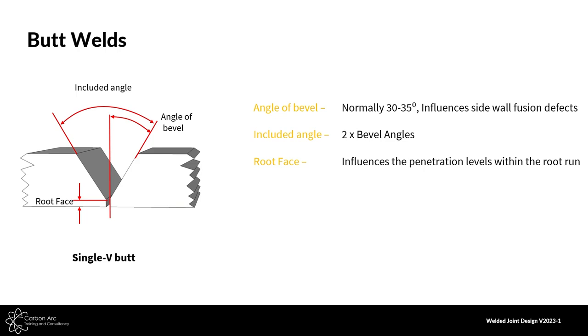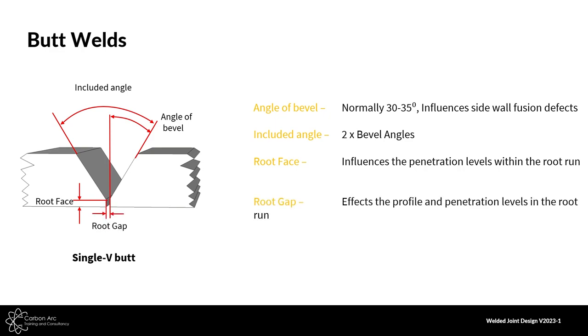The larger the root face, the more difficult it is to penetrate all the way through the material. But if it is too thin, it is more likely that we will get a defect called burn through, where the weld metal collapses and creates a large hole. And then lastly we have our root gap, which affects profile and penetration. The larger the gap, the easier it is for the material to fall through; the smaller the gap, the harder it is for the weld metal to come through.